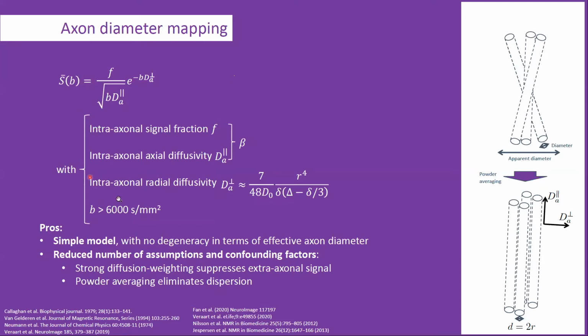That means that we have to go to high b-values. So this model only applies to high b-values of 6,000 or more. But the good thing is there's no degeneracy in terms of the radius, and there's a reduced number of assumptions and confounding factors because we don't have to model the extra-axonal space.